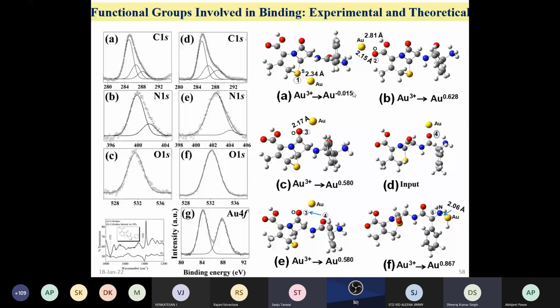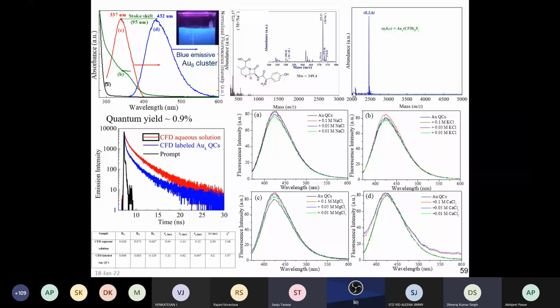So how can we prove that we are successful in making the gold 8 quantum cluster, below 2 nanometer, at pH 6? Actually, it was the basic main result of our research that at pH 6 we got the gold 8 quantum cluster. The gold 8 quantum cluster shows fluorescence-type basic properties. What is that? It means that if you excite this sample at 337 nanometer, we get the emission peak at 432 nanometer with a Stokes shift of 95 nanometer.